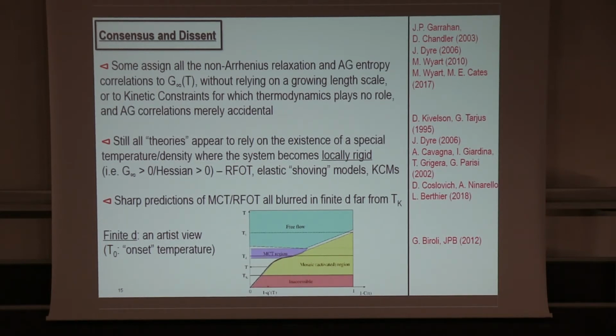And so this idea of something like a mode coupling temperature or a Goldstein temperature must arise from somewhere. And at least in RFOT, there's a well-defined reason for this to happen. I think one of the reasons all this is still very controversial is, of course, that all the length scales, all the divergences are cut off, and length scales are bound to be small in this problem. And so all the sharp predictions of MCT in particular, or RFOT, are blurred in finite dimensions far from T_K,